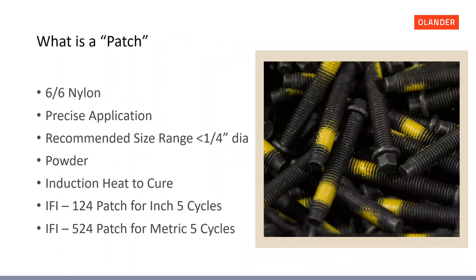Here we see a picture of a patch product on screws. The patch has been applied — it's a 6-6 nylon compound. This is not an adhesive; it's simply a nylon material that is deposited in powder form using an applicator. The bolts are heated using induction heat, and once the powder hits the bolt it adheres itself. Notice the first three threads are left clean so you can start the fastener into the hole. We can adjust the patch up or down or change the size depending on the interface. This meets the IFI-124 and IFI-524 for metric.